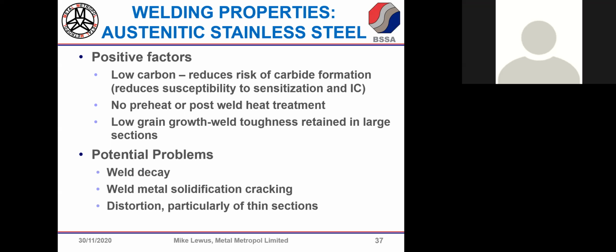It's circumvented by the L grades. You may remember in that 316 list we've got 316L mentioned several times. The L stands for low carbon. Now that's very useful because there's a critical temperature window between about 450 and 900, where if carbon's high, we can get formation of chromium carbides at the grain boundaries, which effectively depletes chromium from the grain boundary area. So subsequently, if that material is exposed to an adverse environment like marine, the first place it's going to get attacked is the grain boundary. So I always draw attention to the fact that if any welding's being done, you want to use either a low carbon grade, an L grade, but we could also choose another option and use what we call a stabilized grade. That's a grade with either titanium or niobium in.